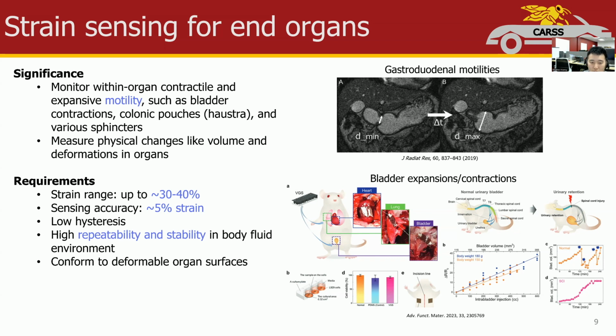However, few studies have solved the encapsulation problem for stretchable strain sensors. Here, we are focusing on the large strain range and good encapsulation inside a liquid environment. We want to achieve 30 to 40% strain while having good encapsulation for several months. This is new and also very challenging because our strain sensor is using a unique wrinkle Parylene encapsulation.